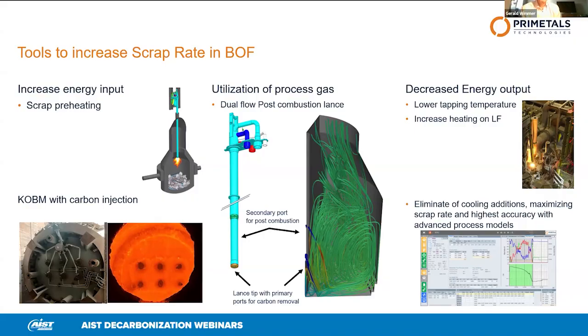For higher scrap rate, we need better mixing, and this we can do with combined blowing in a converter like KOBM, as is shown on the very left side picture. We're just doing a new project for KOBM for a customer in Korea. So this is a very special niche technology, but a nice one when it comes to metallurgy and to scrap rate. So for higher scrap rate, 30 to 35%, KOBM converter has an advantage thanks to its better mixing.